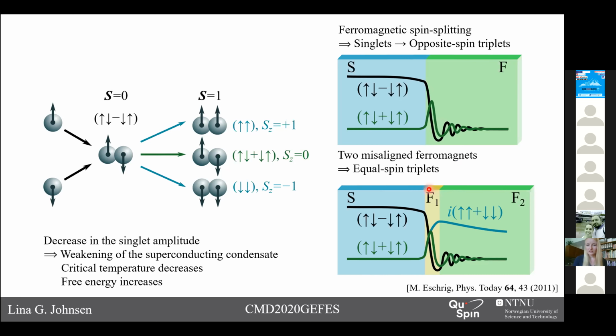If we instead include a second ferromagnetic layer which is misaligned with the first one, then the misalignment between the magnetizations rotates the opposite spin triplets into equal spin triplets. And since these are already aligned with the magnetization, they can survive for much longer distances inside the ferromagnet. Also, since the creation of these is dependent on how much the ferromagnets are misaligned, this effect depends on the direction of the second ferromagnet. So we can control the singlet amplitude by rotating one of the ferromagnets. In this way, we can control the critical temperature and the free energy.